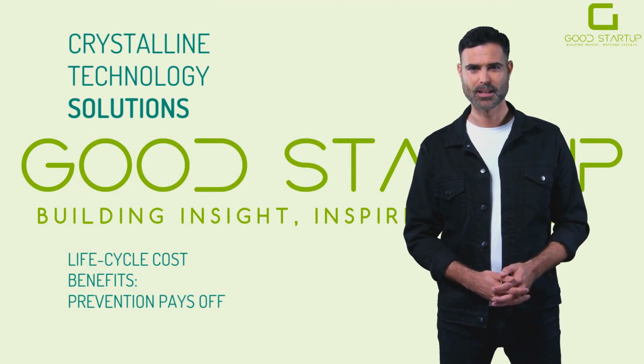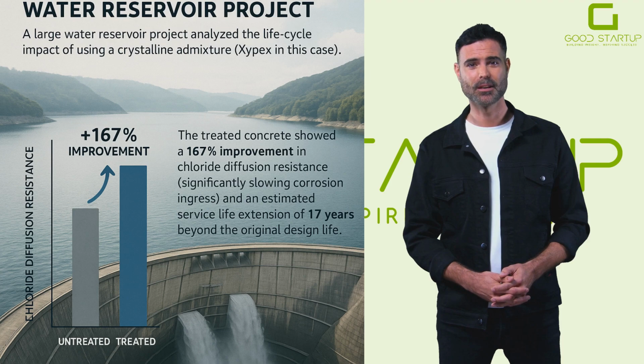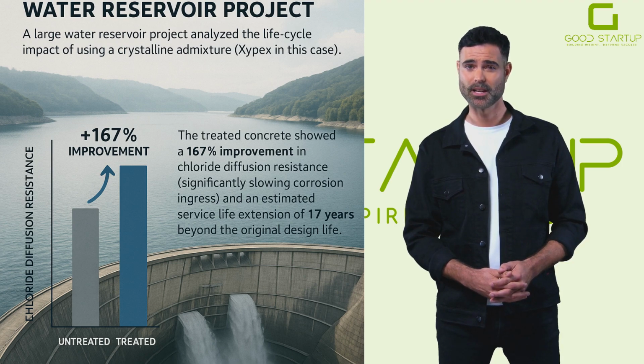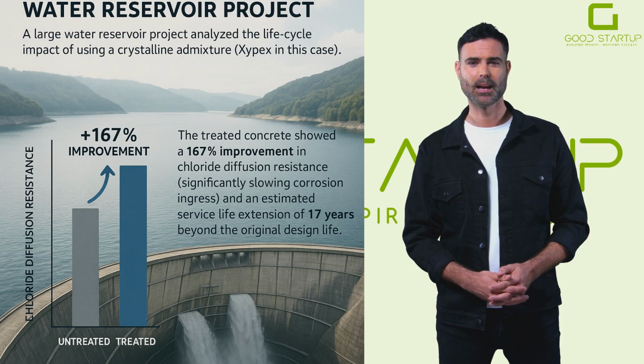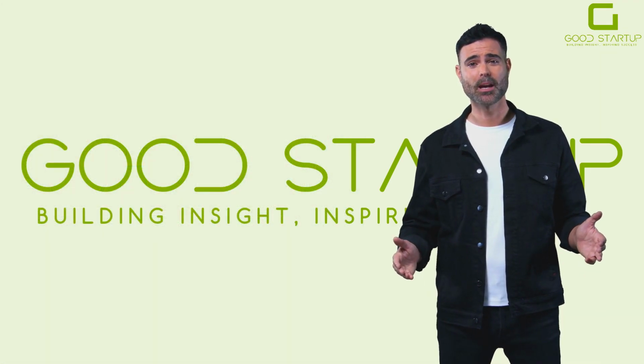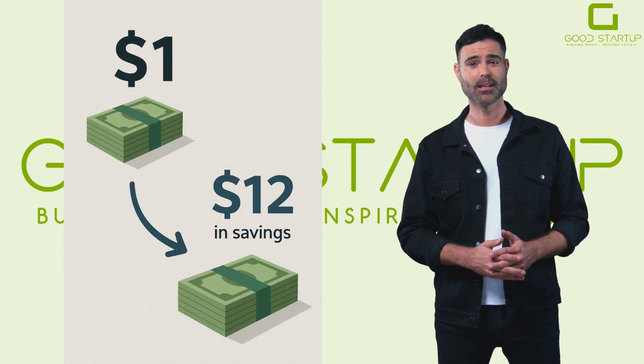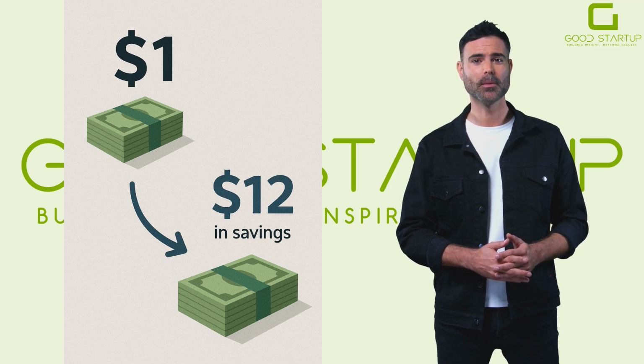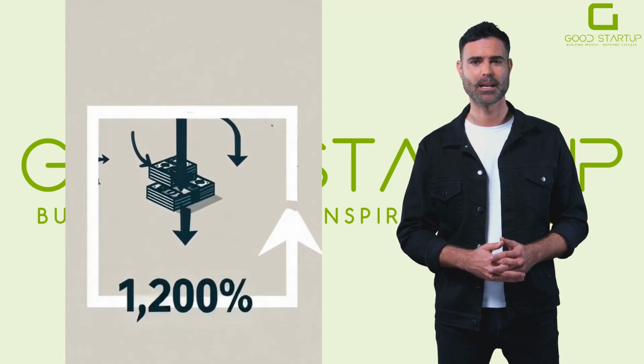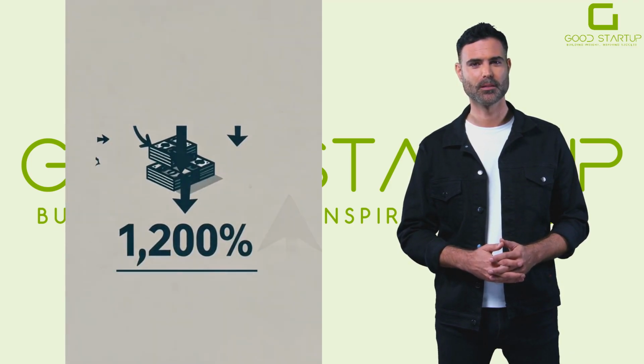Consider a real-world case study. A large water reservoir project analyzed the life cycle impact of using a crystalline admixture. The treated concrete showed a 167% improvement in chloride diffusion resistance, significantly slowing corrosion ingress, and an estimated service life extension of 17 years beyond the original design life. The life cycle cost analysis found that this extended longevity and reduced maintenance translated to a 12-fold payback on the cost of the admixture. In other words, every $1 spent on the crystalline additive yielded about $12 in savings over the life of the structure. That is a 1,200% ROI in financial terms, an extremely sound investment by any standard.